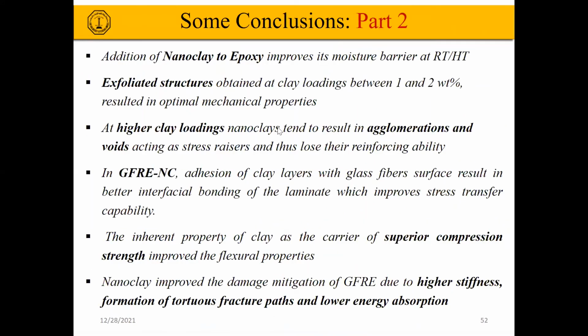Finally, we conclude, this is for the second part, that addition of nanoclay to epoxy improves its moisture barrier at room temperature and high temperature. Exfoliated structure was obtained for clay loadings between 1% and 2%, and these resulted in optimal mechanical properties. Higher clay loadings result in agglomerations and voids, which make them lose their reinforcing ability.